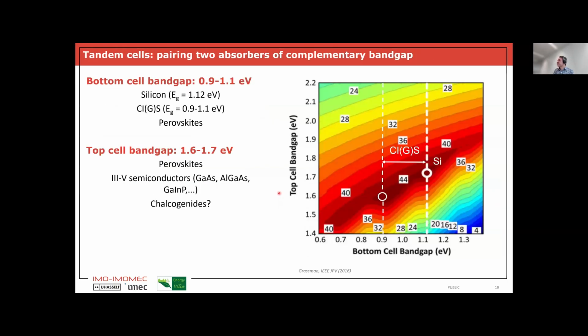And there, of course, we have the same thing as before, because it's a silicon bottom cell. But theoretically, this means, whereas with a single junction silicon solar cell, you can reach only 29.4%, here we see that by going to a tandem device with a bottom cell of silicon, which has a 1.1 eV band gap, in principle, it is theoretically possible to reach efficiencies up to 40 to 44%, so much higher.